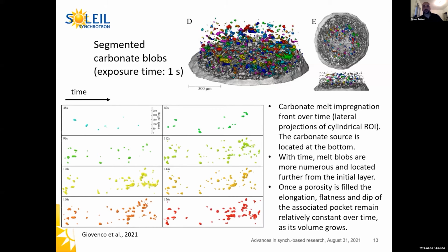And here you have the evolution of this melt propagation with time. Each frame, at the bottom, is the location of the original carbonate layer, and the height of each frame is the silicate matrix. So it's a lateral projection, and it reads like this from top to bottom. What the authors saw in this paper is that with time, melt blobs are more numerous and located further from the initial layer. And once porosity is filled, the elongation, flatness, and dip of the associated pockets remain relatively constant over time as its volume grows.